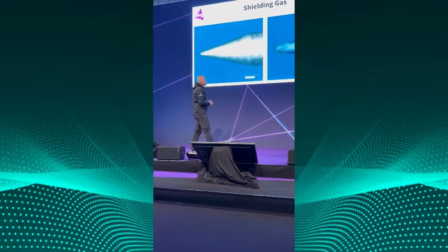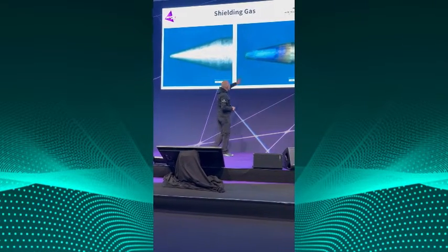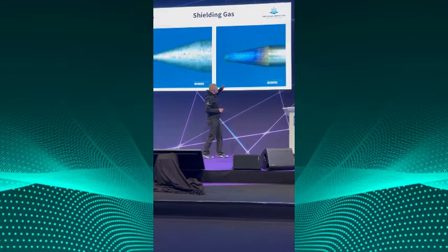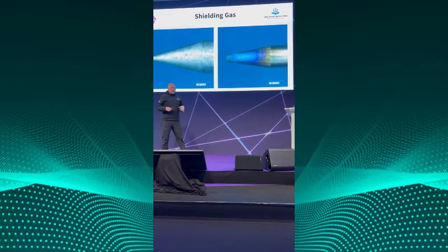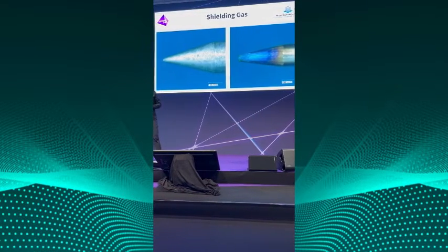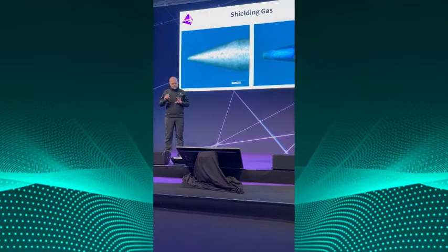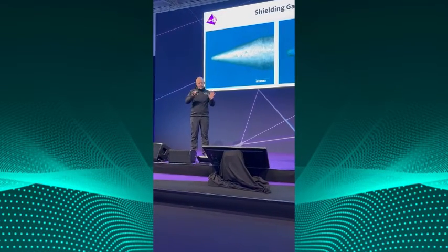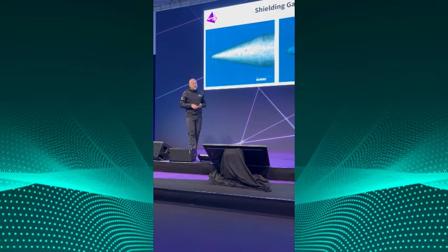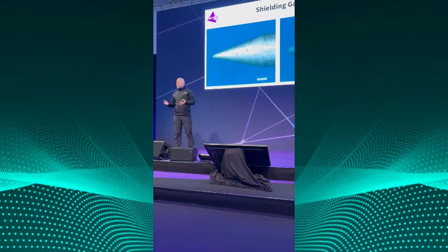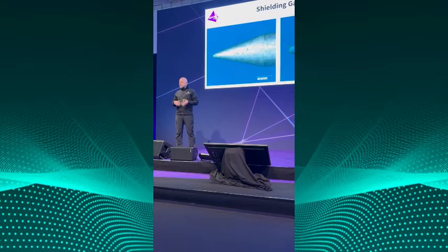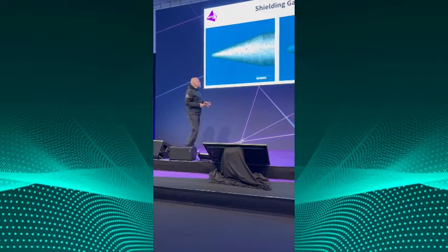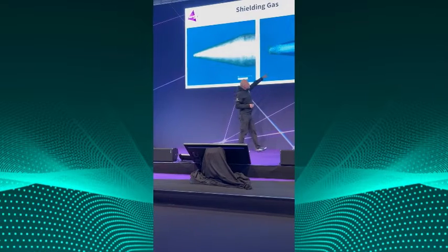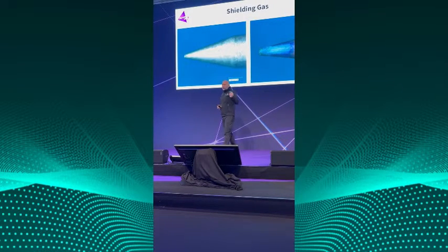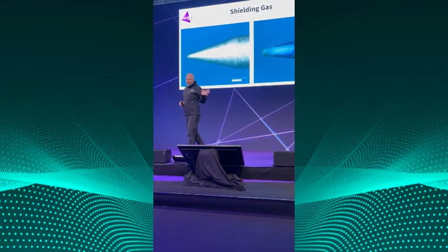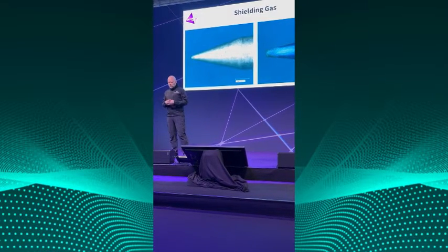On the right side, you see a discoloration people are certainly familiar with. These colors are caused by non-stoichiometric tungsten oxide, so very high oxides, like tungsten 19, oxygen 38, something like this. They will decompose in an arc because they are not very stable oxides. So if you have discoloration, that's almost always caused by too short of a pre-flow time. So while the tungsten is cooling down, it will be exposed to oxygen.